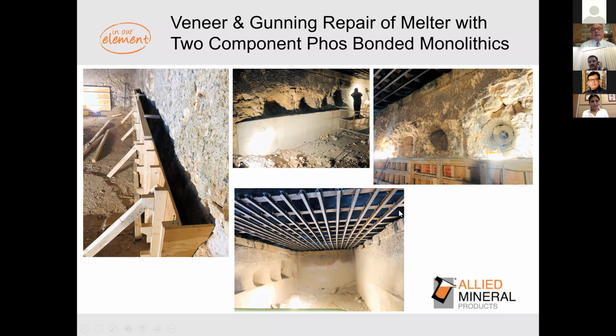I'm sure all of you that have worked in an aluminum foundry have seen this many times. And what we have done with this furnace is we've veneer cast the lower sidewalls, and then we gunned the phosphoric acid bonded material in the upper side wall to repair around the burner ports and bring the wall back to its original thickness. And what we're seeing with this is, to get the furnace to this condition here, it took, say, three to 4 years, and they've lost this much. When they veneer cast, we have found that you can add another 3 years of life.